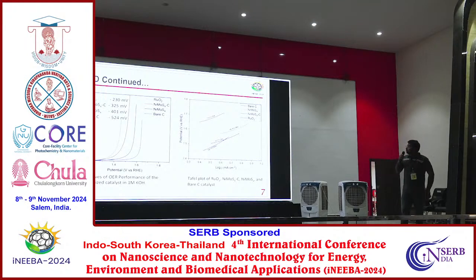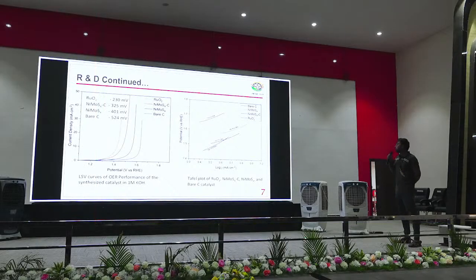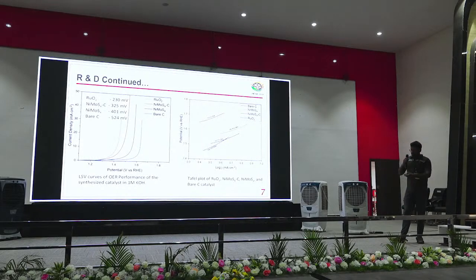This is the OER performance of the nickel molybdenum catalyst compared with ruthenium oxide. In OER, ruthenium oxide is the benchmark catalyst, which occurred at 230 millivolt. It is compared at eta 10. Nickel molybdenum sulfide with carbon was 325 millivolt, nickel molybdenum sulfide 401 millivolt, and bare carbon was 524 millivolt. Tafel plot of ruthenium oxide 54, nickel molybdenum sulfide with carbon 62, nickel molybdenum sulfide 76, and bare carbon sphere 101 millivolt per decade.